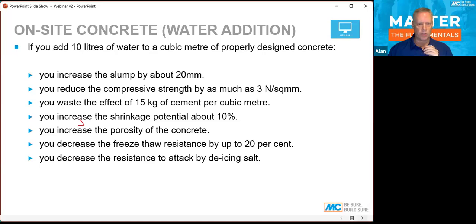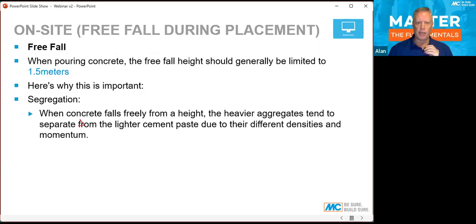Second one, dropping concrete from a height. How many times do we go on site and we see a column or a wall that has honeycombing and segregation, and then we find that the concrete was dropped right from the top? The concrete should be generally dropped from no more than 1.5 metre height. And that is clearly just to prevent us from having segregation. Aggregates will fall faster than the cement paste. Laws of gravity. So if the drop is higher, then it's much better to use tremie pipes, concrete pumps, or chutes that can control the placement and minimize the segregation.